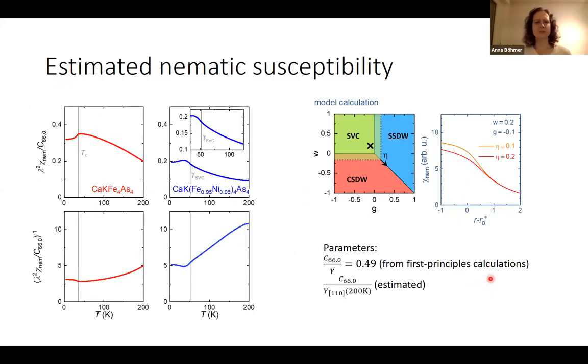So what does it mean for the nematic susceptibility? These are estimates for the nematic susceptibility from these data. There are a few parameters here, but the qualitative temperature dependence doesn't depend significantly on these parameters. So we are very confident about how this looks. The nematic susceptibility in this one compound, this pure one, increases but saturates, flattens, and then decreases below Tc. That looks like a sign of competition, as we are very familiar with already.